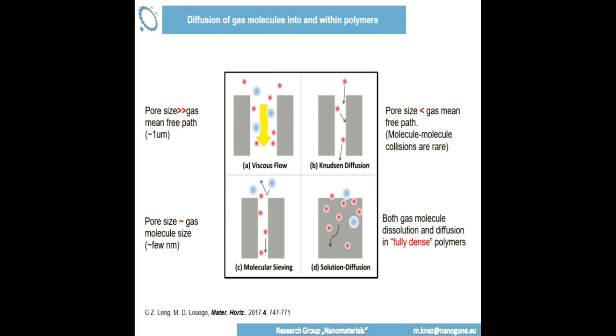So we were considering for pores several possibilities here. You have the Knudsen diffusion. Depending on the pore size, some people think about the viscous flow, so this is also a possibility to make a model system. If the pores are very, very small, you have molecular sieving. But if you don't have pores as such, if you just have a substrate which is less dense, it means the porosity is on the atomic level, you don't have a diffusion mechanism of that kind. You have a solution diffusion, so you need to consider your substrate not being a physically porous structure. You have to consider your substrate being a liquid, a very viscous liquid, where materials dissolve. And the materials which dissolve are basically your ALD precursors. So they are coming to the solvent, the substrate is the solvent, they are dissolving there, and they need to diffuse through the polymer if they are able to do it.